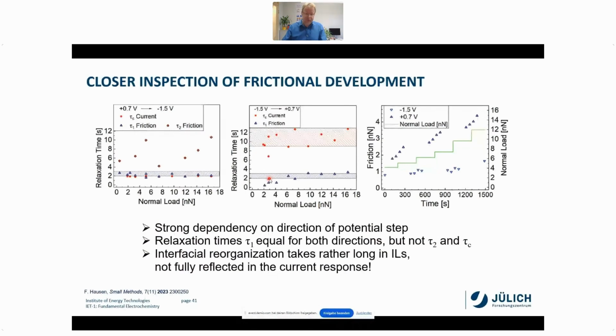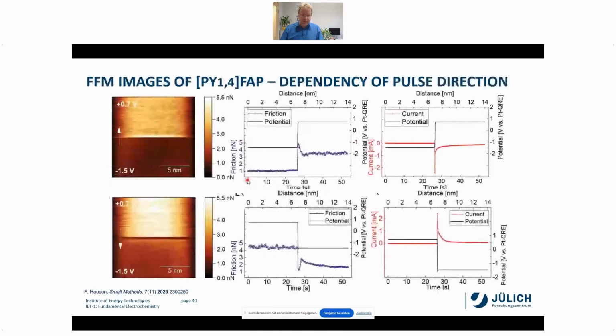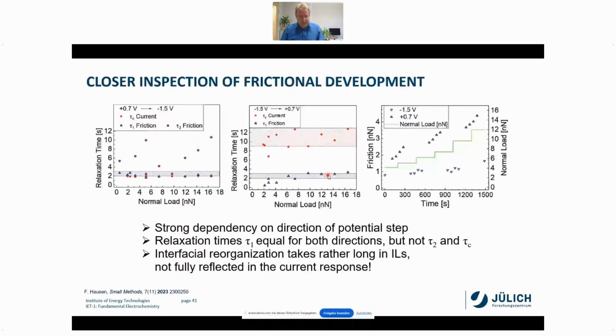And the first relaxation times, so if I go back, the first times until the friction stabilizes here, are rather equal for both directions. So from that, we can learn something about the real switching behavior if we have energy materials in that.